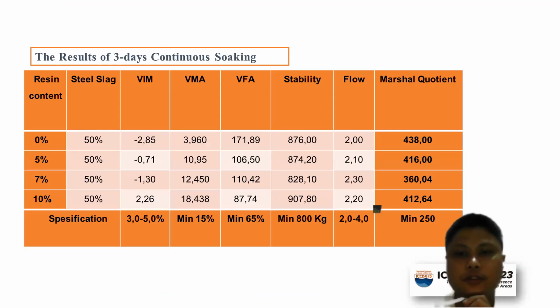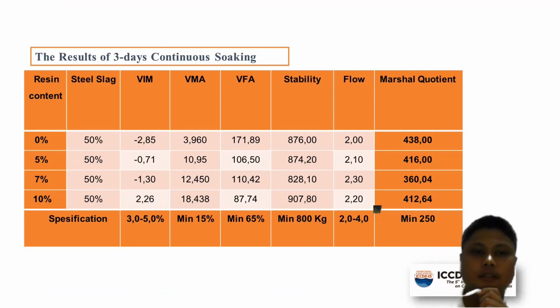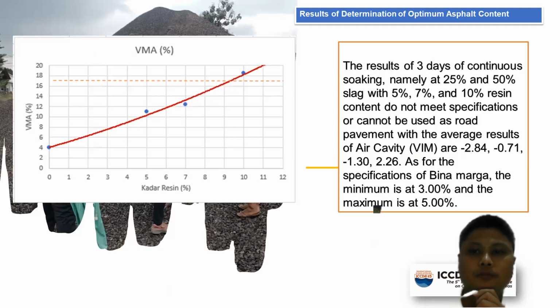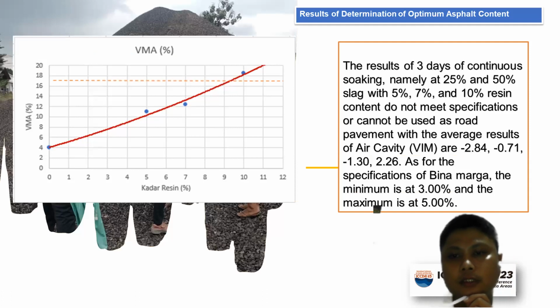And the result of continuous soaking, we have a stability of 876 and in the resin content of 10% we have 907.8. This is the result of 3 days continuous soaking. For the result of the asphalt content, the result of 3 days of continuous soaking, namely at 25% and 50% slag with 5%, 7%, and 10% resin content do not meet specification or can't be used as road pavement,